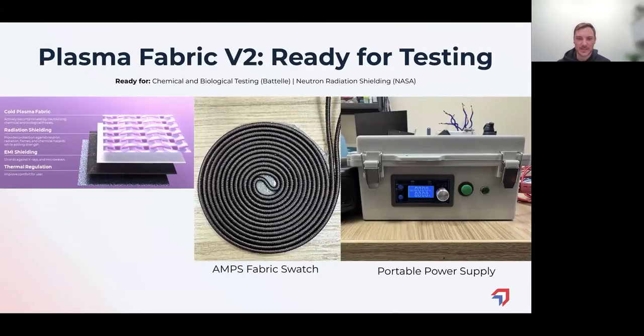So the very center is what the form factor looks like right now. We were able to take that coaxial fiber and wind it up into a spool. And just as a basic feasibility, we were using lamination to put all of our different layers together. So the outside is this cold plasma fabric. Underneath that is our radiation shielding layer. Below that is some EMI shielding as well. And then the final layer, which is closest to the warfighter, is for thermal regulation.